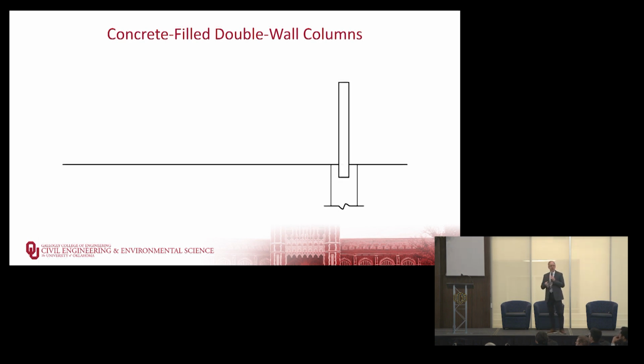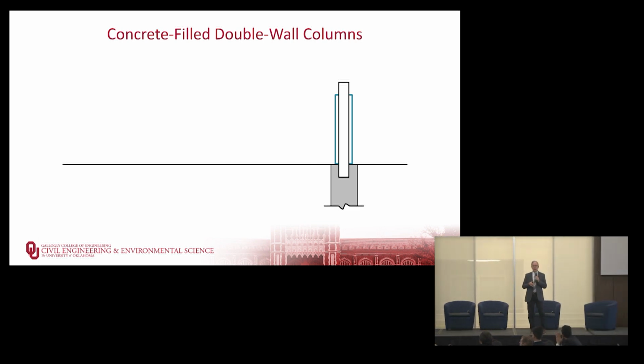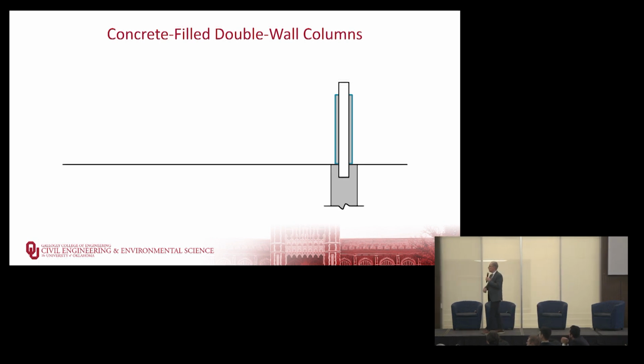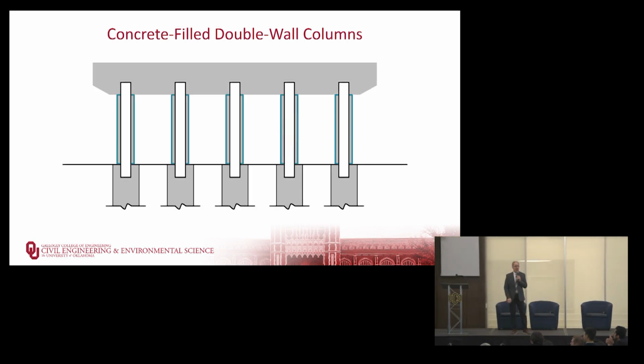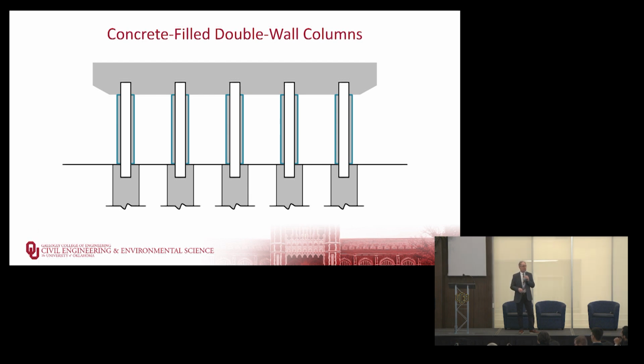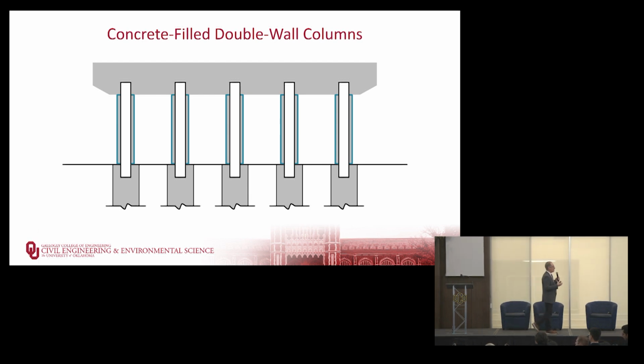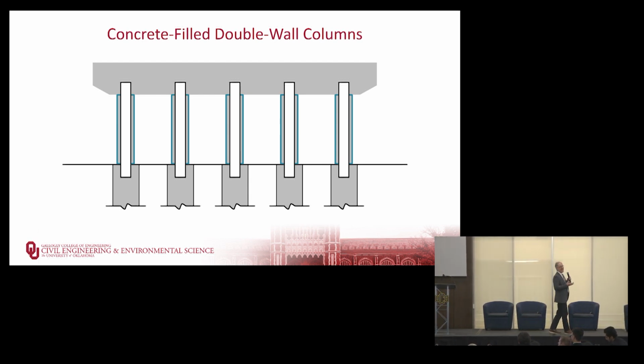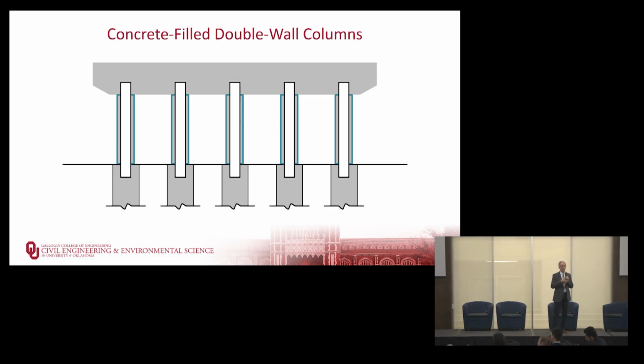Put in your steel tube, get it in the right place, cast the concrete for the drilled shaft, come back and put the FRP tube on it, and then cast the concrete in the interstitial space between the steel tube and the FRP tube. And then you do that for all of your bridge columns, put the pier cap on, and you're done. So you could cast this column in a day. As soon as you put the steel tube in, cast the drilled shafts, come back the next day, throw the FRP tube on, cast the concrete in the middle, the column's done.